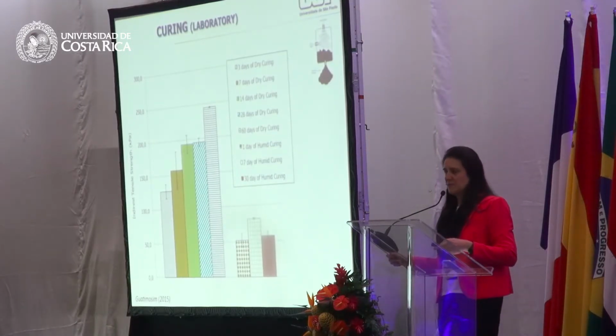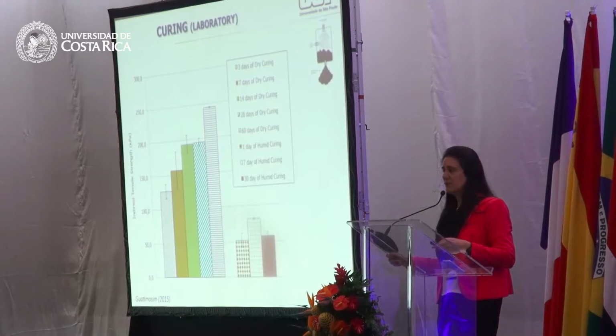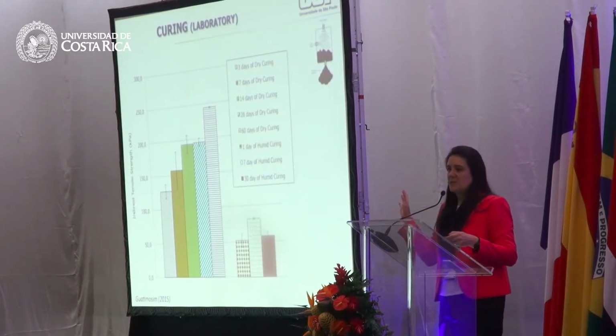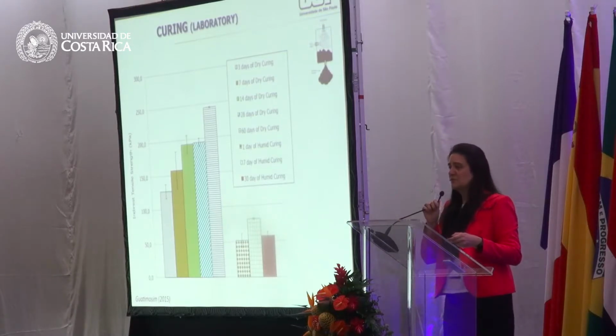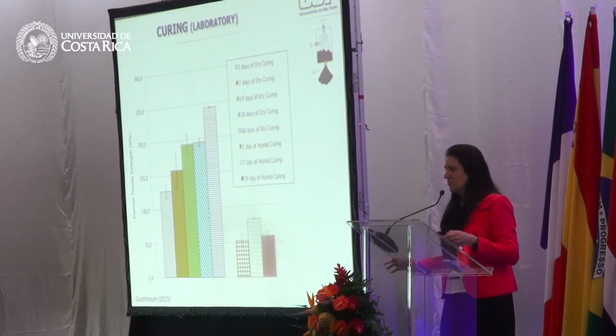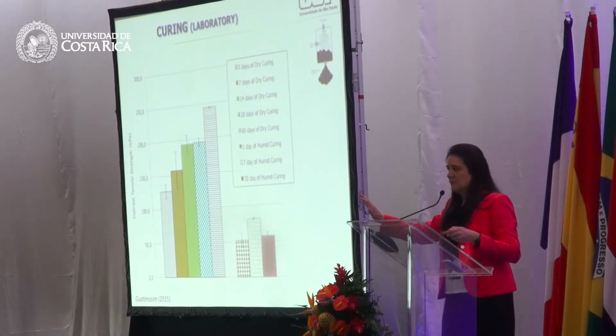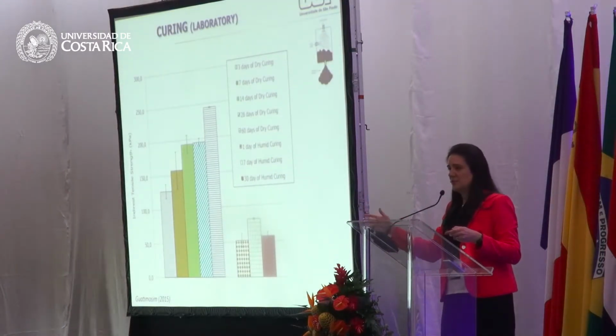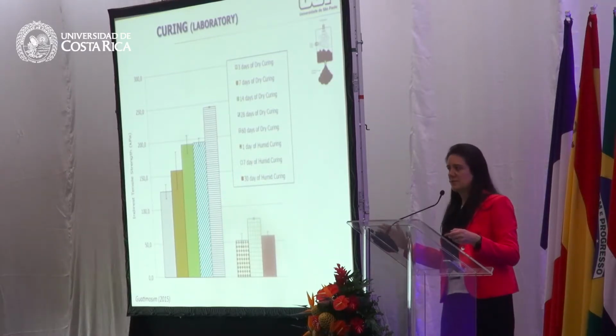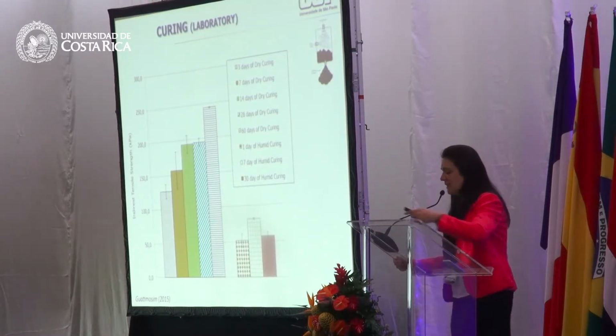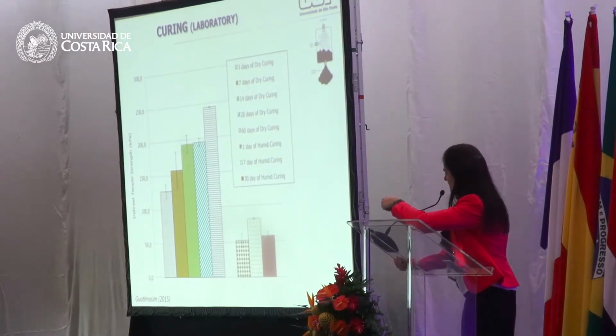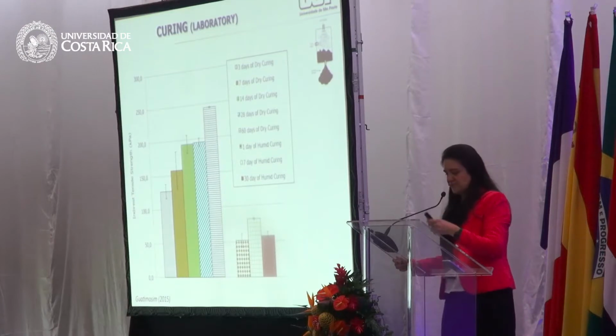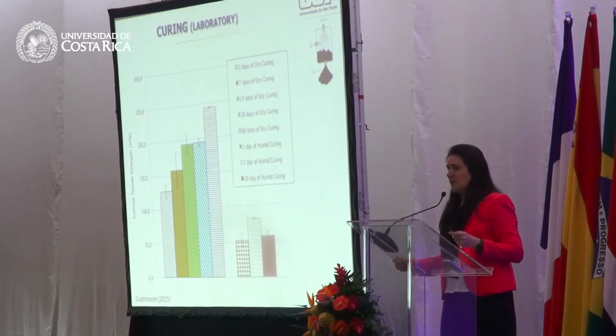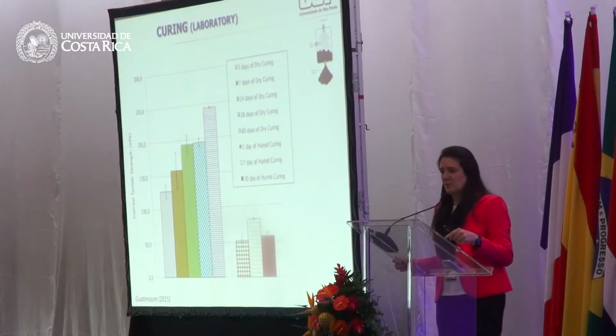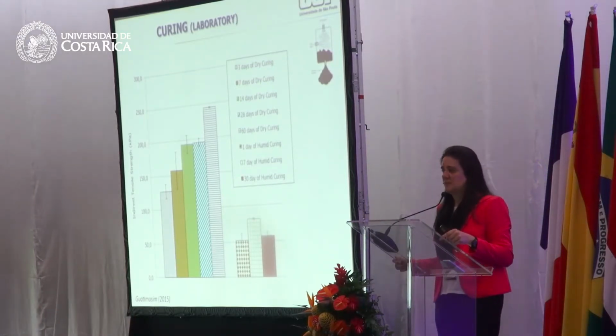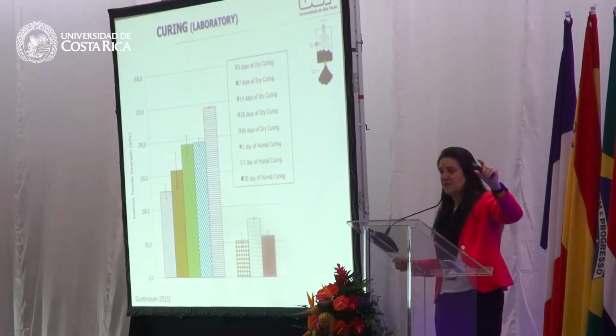The curing process, we've run a couple of tests on that too. And what you see in this plot is two different types of curing. We call the first one the drying process. We just put the specimens in a controlled temperature, 25 degrees C, and wait for a certain amount of time. And we can clearly see the increase in the ITS. And then we thought, okay, but in the field, this water does not come out so fast because we have a surface layer on top of it.